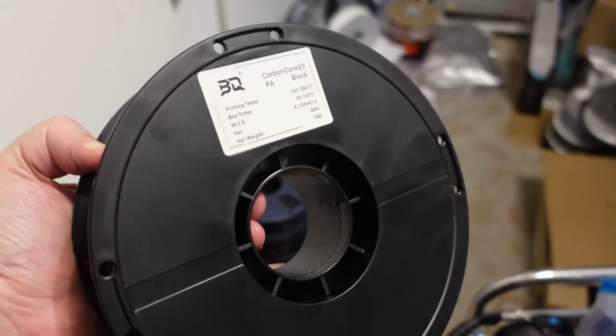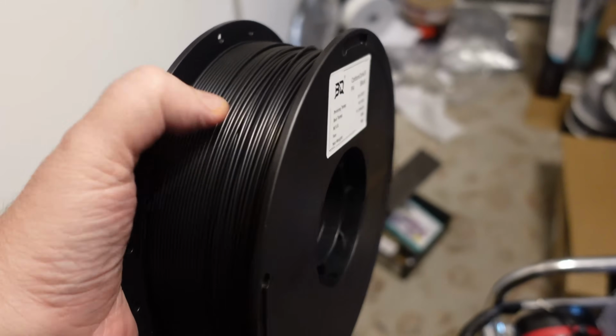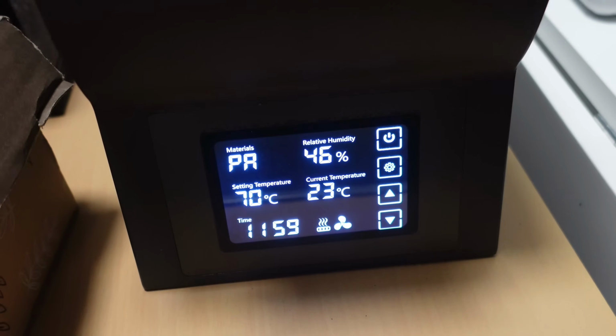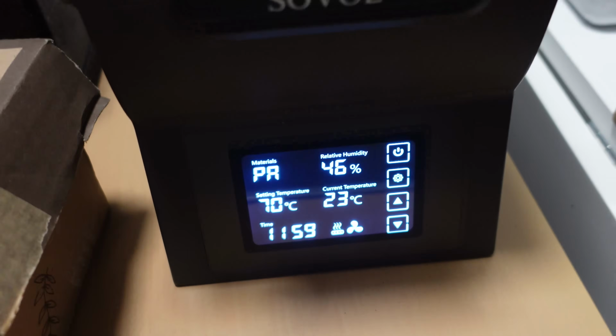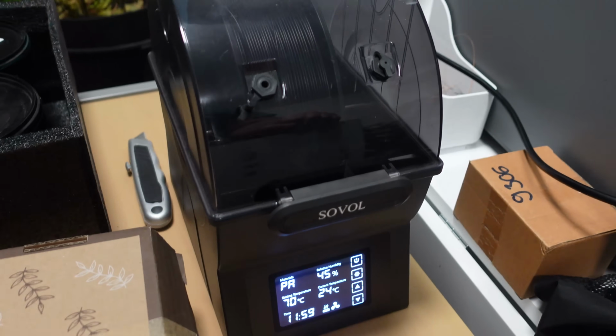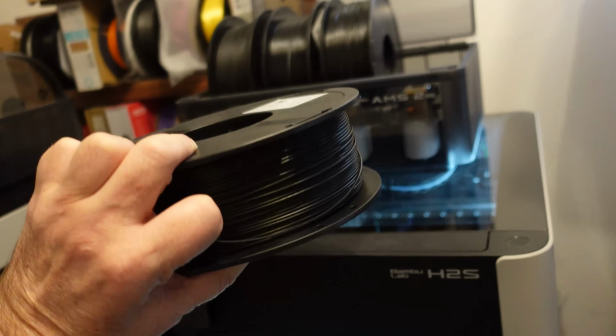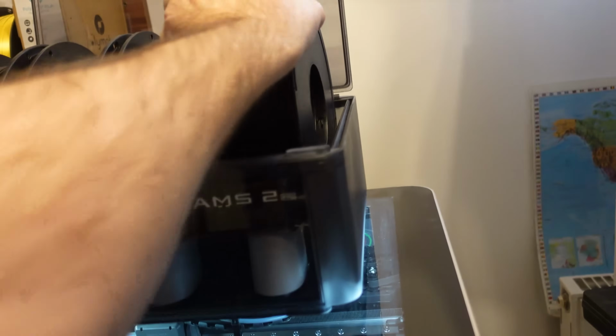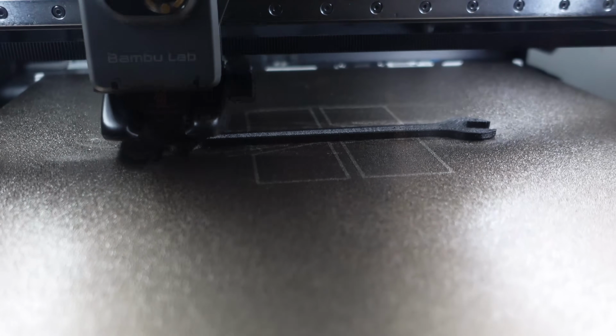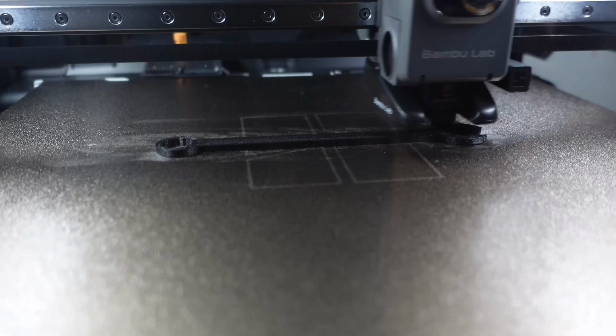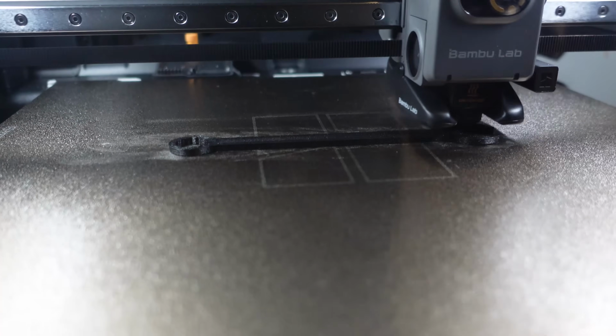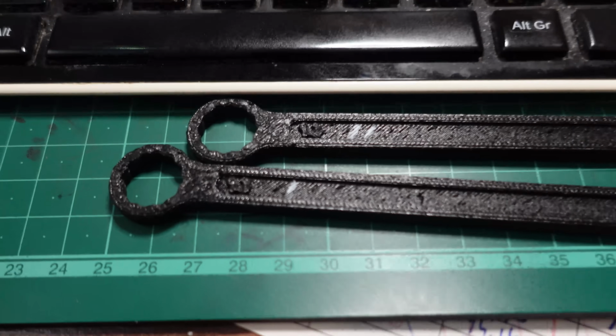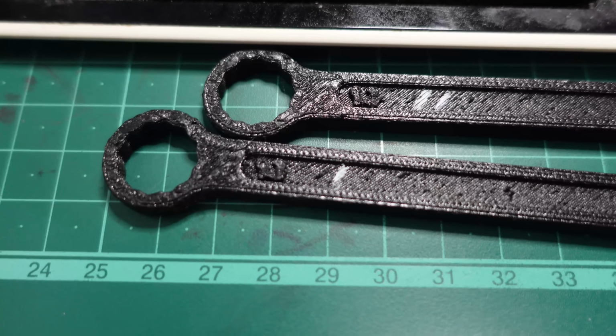Additionally, this kind of spool will result in drying only the outer loops because it is too tight. I hope 70 degrees Celsius for 12 hours will give us some better result. Probably the outer loops are more dried, but it's time to test it again. Looks a little bit better, but far from perfect. I don't know how they stored this filament, but the improvement is hardly visible.